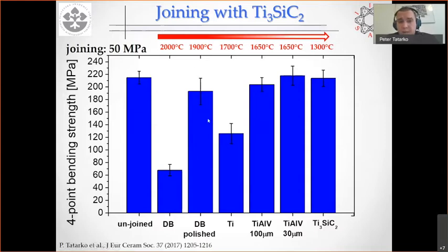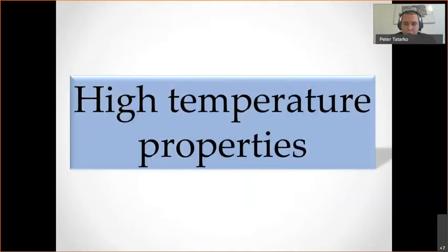The important thing is, you look here, we started from 2000 degrees C and we lowered the temperature down to 1300 degrees C, which is a significant reduction. So in other words, we only use 1300 degrees C, but we retain the same strength of the materials, which is a very important feature. That's why we also wanted to see how these joints perform, because as I mentioned at the beginning, these joints were supposed to perform at higher temperature and in extreme environments. So we needed to know how these joints will perform at high temperature.